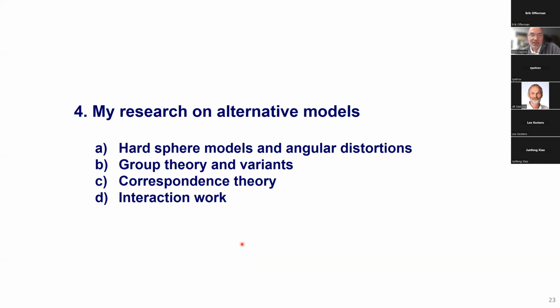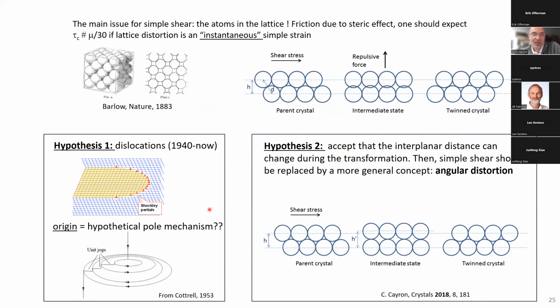So that's why I introduce my own research on the subject, and I will start with hard sphere models. Because we know that the atoms in the lattice are not bricks. They are more spheres than bricks. So if we want to apply a simple shear to go from this position to this position, with a continuous simple shear model, we are in trouble in the intermediate position because the interaction between these two atoms is too strong. So it's impossible. We can even calculate that the shear value would be of the order of the shear modulus. So that's really impossible.